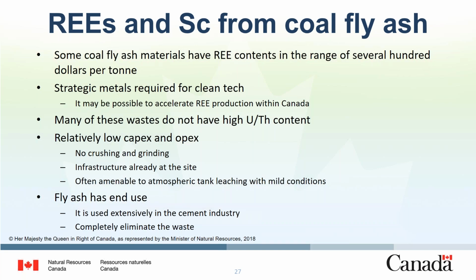It has relatively low capex and opex, so no crushing and grinding. Infrastructure is already at site, and these materials are often amenable to atmospheric tank leaching with mild conditions, which basically is a very cheap process. And one of the most important reasons is fly ash has an end use. It's used extensively in the cement industry, which means we completely eliminate the waste, which is a really attractive feature.